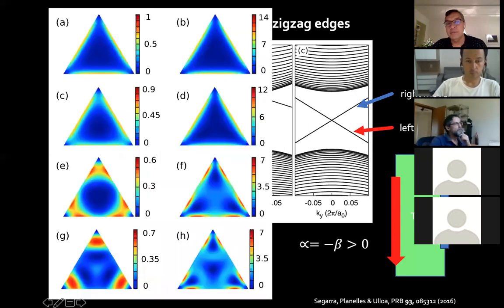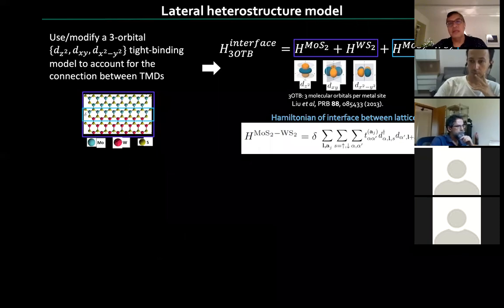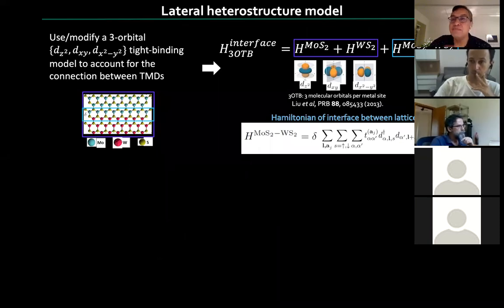Now Carlos, my student at the time, did some calculations. And indeed, if you have a triangular flake, you look and there are these states that are well-defined on the edge, in this case an edge, not an interface. They're there. So one expects these states to be there. So now we want to describe them better.